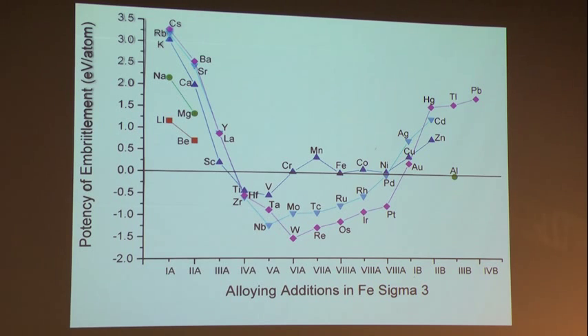This was then used to design the first of what we've called our quantum steels, where by designing new compositions to control grain boundary composition, coming directly from a quantum mechanically predicted genome, we have completely eliminated the intergranular mode of stress corrosion cracking in these very high performance steels.